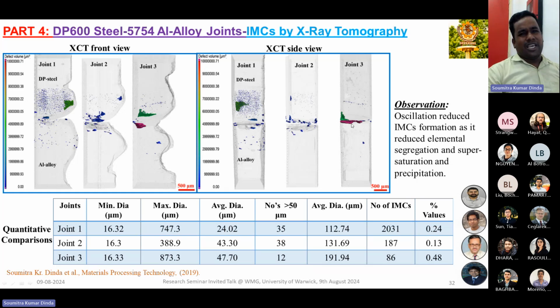And where we see again the same thing, that means the intermetallics are formed but there are different ranges. You can see the scale of the volume in micron cube, and see the quantitative result. And now we see the total scan area. What is the percentage value of the intermetallics formed? So for joint 1, it's showing 0.24%, but in case of joint 2, it's 0.13.